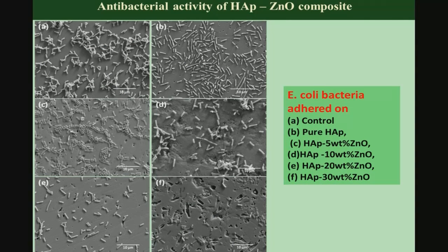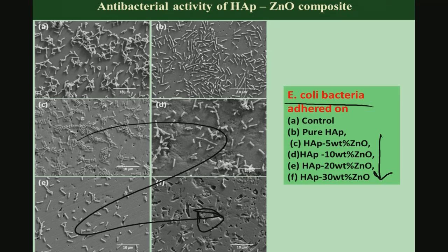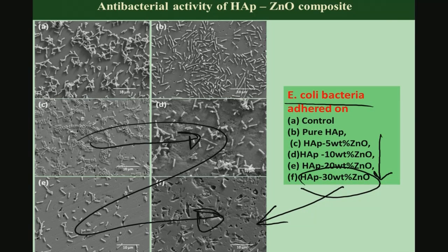In terms of antibacterial viability, when E. coli — a widely used bacterium with rod-shaped morphology — is grown on hydroxyapatite-zinc oxide composites, as zinc oxide content increases, at the highest level of 30 percent zinc oxide, hardly any bacteria are seen. Certain features on the material surfaces indicate that zinc oxide is leached out, causing bacterial death. Colony formation ability is also reduced, with bacteria appearing in isolated rather than colonized conditions.